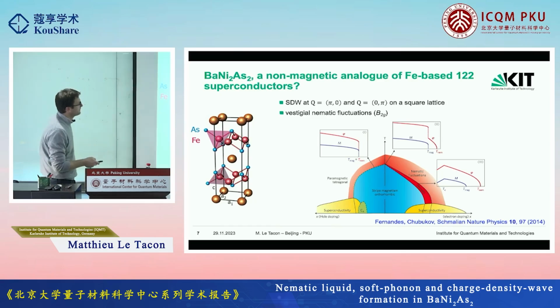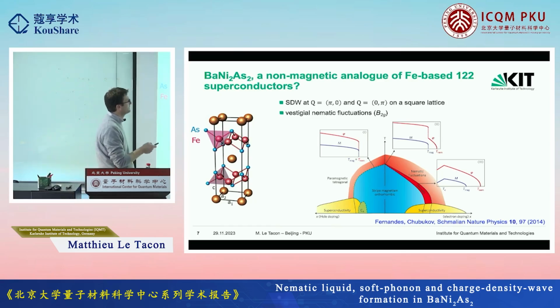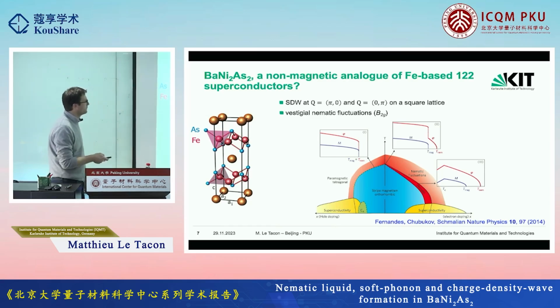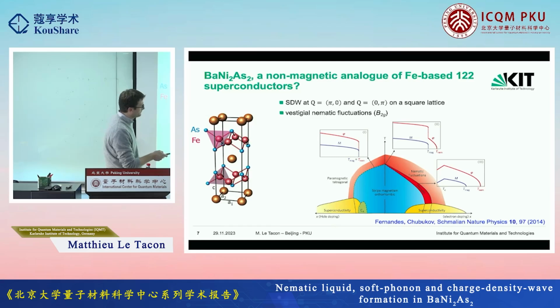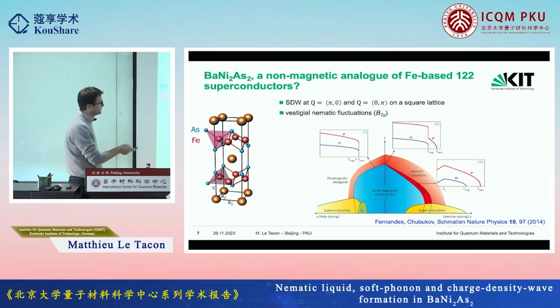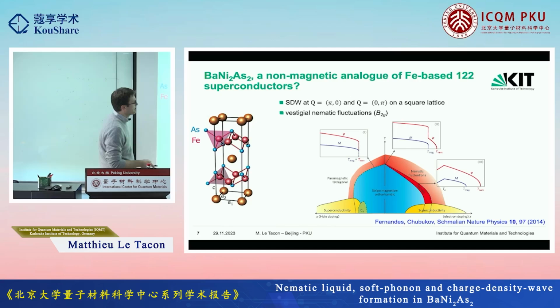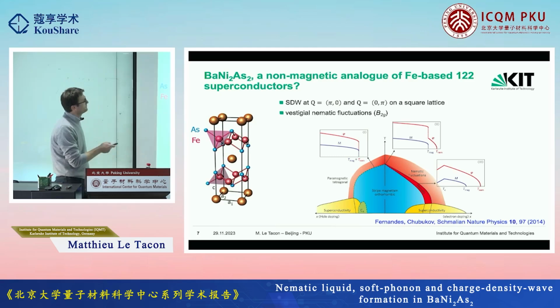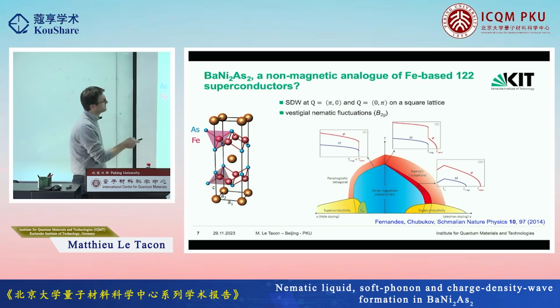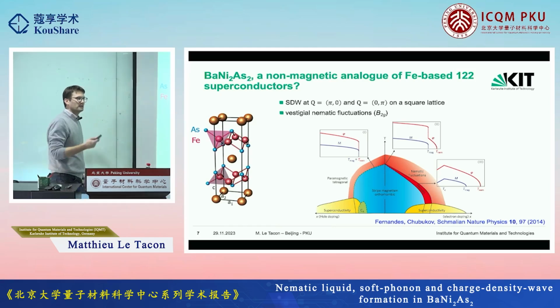And those particular materials are very interesting, and there's been a lot of discussion about electronic nematicity, which is understood in this phase diagram. So the compound has at zero doping, so half filling, the parent compound here exhibits a magnetostructural transition. So there is some kind of stripe magnetic order that forms and an orthorhombic distortion of the lattice. And before it forms, you get some kind of nematic fluctuations. The way to understand that is that you have pretty much a doubly degenerate magnetic order at Q equal pi 0 and Q equal 0 pi on the square lattice.